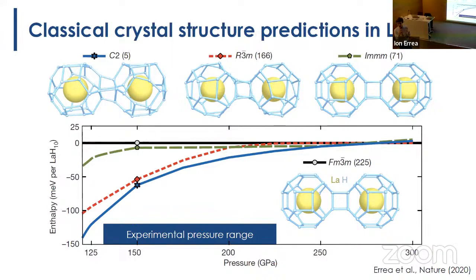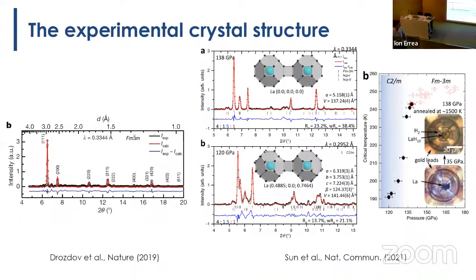When you do that, you find these kinds of distorted structures. They are distorted versions of this high symmetry structure, and they have much lower enthalpy at this pressure. In the experimental pressure range where this material was found to be a high TC superconductor, around 250 Kelvin, this structure is not the minimum in the Born-Oppenheimer energy surface. These others have much lower energy. But experiments are stubborn and they find precisely this high symmetry phase, down to at least 130 GPa. So it's about 100 GPa below where these structures are not found in the calculations. Experiments tell you that it's still this high symmetry phase.